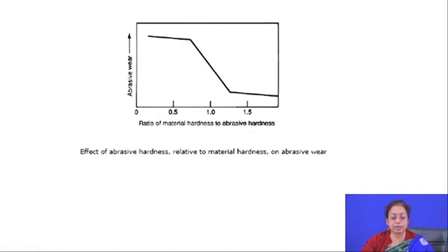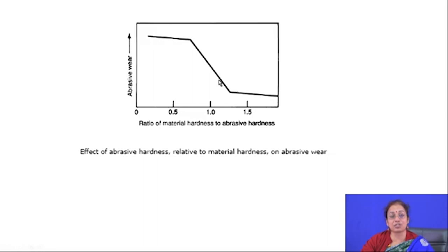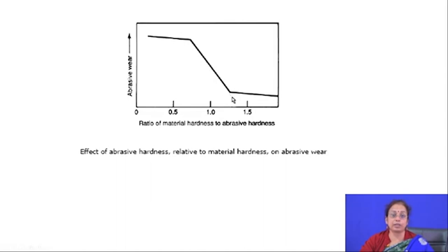Almost all kinds of abrasive wear can be prevented by increasing the hardness of the surface. The optimal level is 1 to 1.25 times the hardness of the mating surface — this minimizes wear rate without causing excessive wear on the mating surface. If the hardness difference is too large, wear will occur on the other mating surface instead.